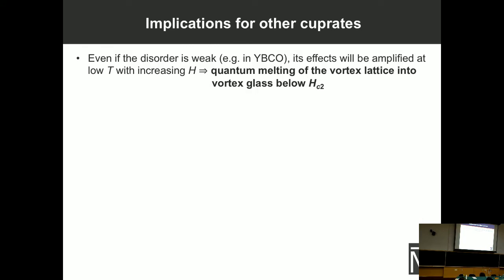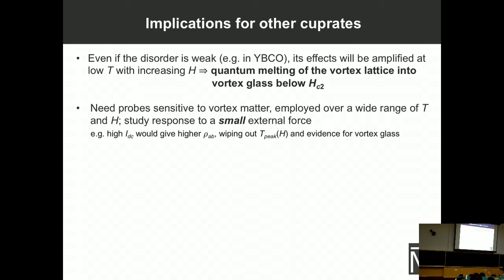Well, this is an illustration of what some people would expect: that the effects of disorder obviously have to become important at low temperatures. And so even if the material is very clean, such as YBCO, it is established that it does have some disorder, and one can expect that its effects will be amplified at very low temperatures. So one really needs to go to much lower temperatures, which was not done, and apply a small external force, which also has not been done up to now. And of course, one needs to use techniques that are sensitive to vortex matter.